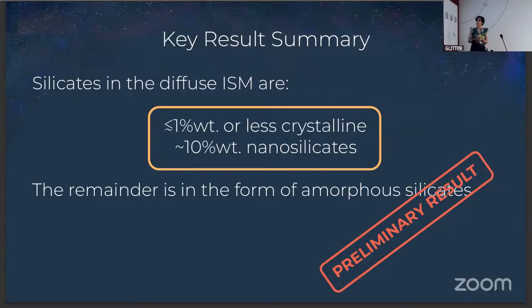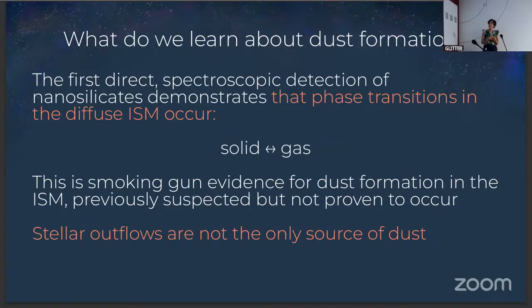So once again, the results of this project so far are that in the diffuse ISM, with extinctions of AVs between 4 and 8, we find very little crystalline silicates, less than 1% by weight, but we find about 10% by weight of nanosilicates, and the remainder of the silicates are probably amorphous. This provides us with the first direct spectroscopic detection of nanosilicates, which indicates that phase transitions between the solid and the gas occur in the diffuse ISM. We interpret this as smoking gun evidence for dust formation in the ISM, previously suspected to occur but not yet proven. It means that stellar outflows are in fact not the only source of dust in galaxies.